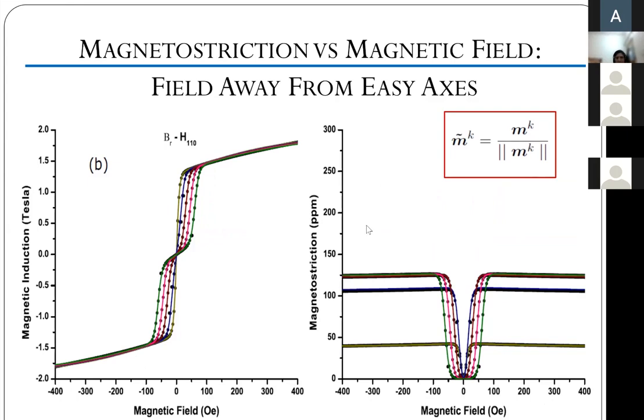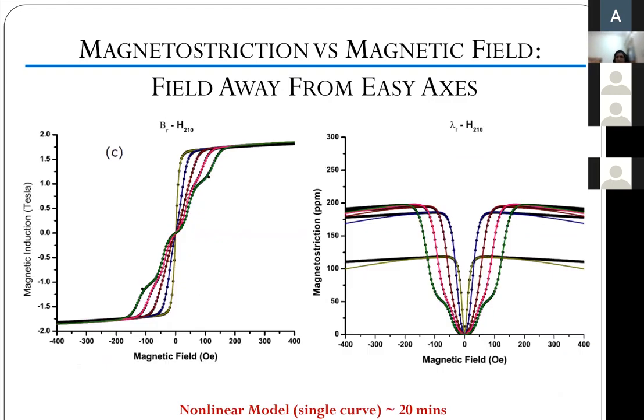We also did this as we keep moving farther and farther from the easy axis. So 100 being the easy axis, when the field was applied at moderate axes. If you remember, there was a hard axis, there is an easy axis, and there is a moderate axis. Even at the moderate axis, there was a lot of success with the model, still with the same level of computational efficiency that we observed before.